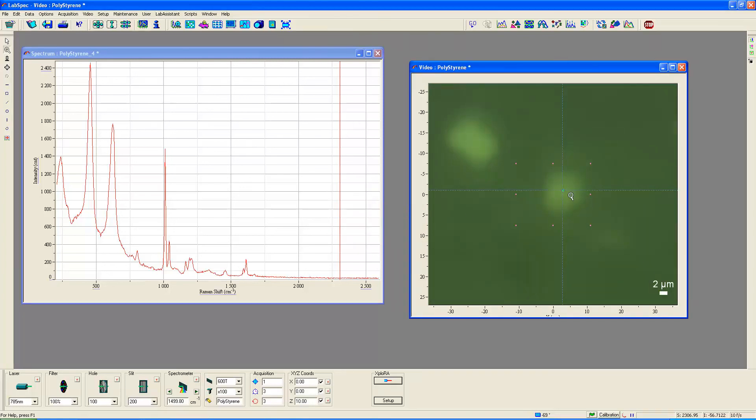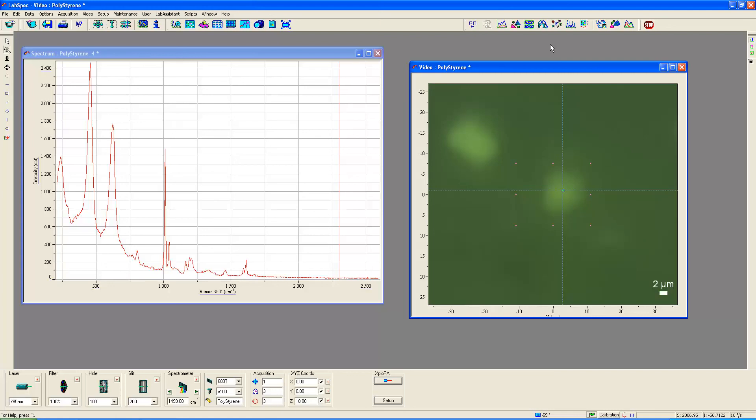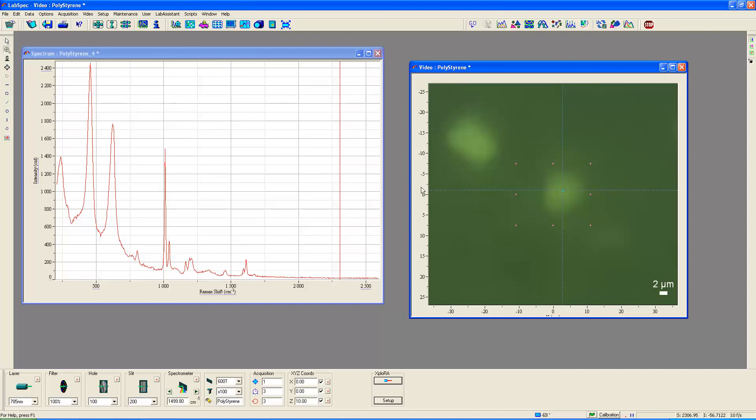And lo and behold, what do you see is below the surface these white particles. Well, these are basically little clumps of titanium dioxide that have aggregated. I presume they would have been put in to disperse uniformly through the polystyrene. But there are areas in which they have aggregated. And so what we see is that if we get below the surface, then we can confocally find these areas of different composition.